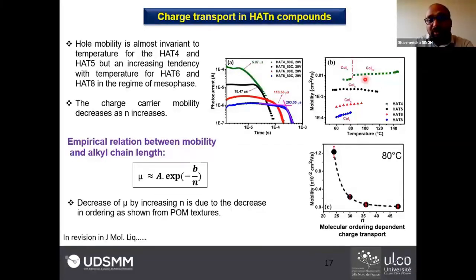So as I told you earlier, the charge carrier mobility significantly depends on the molecular ordering. That's why we recorded the maximum mobility in the HAT4 and minimum mobility in the hexagonal columnar phase of the HAT8. So only we recorded in the mesophase here. One more important thing you can find here is that the charge carrier mobility in the hexagonal columnar phase is lesser than in the hexagonal columnar plastic phase, because the plastic phase is more ordered as compared to the hexagonal phase.